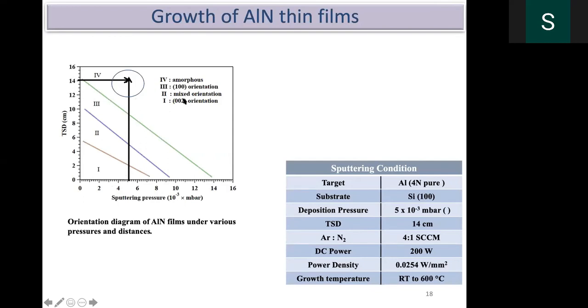When the target to substrate distance increases, the number of atoms that go and stick to the surface is very small, and if the substrate temperature is not sufficient to grow as crystalline, it will become amorphous. And if it is close by, the structure will become crystalline, because the further incoming atoms that bombard the surface transfer some energy to the already existing adatoms. Because of that energy, the crystalline structure forms. That's why, if you reduce from 12 to 10, in this zone you can see 100 orientation, which is very, very important.